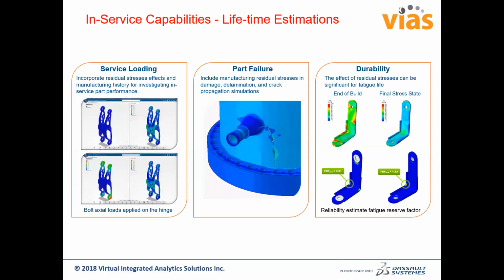And also from the effect of residual stress: if you have a component with and without residual stress, you will see that the fatigue lives are different. So bringing in residual stress is extremely important if your concern is fatigue life. And to initiate a crack, residual stresses may or may not help. Residual stress is self-equilibrating, so through the thickness, the total force coming from the residual stress will be zero. There will be tensile residual stress and compressive residual stress. If you have a micro crack in the tensile region, then most likely it will grow into a dominating crack. These are some of the things you will have a closer look at, because now the simulation helps you look into the physics of the problem that went through the manufacturing process at a much finer level of detail.